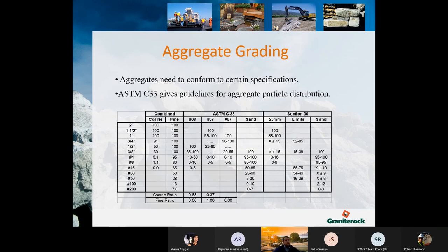There are common gradations for concrete, and ASTM C33 really gives the guidelines for that. A common one is an 08 gradation. So that's going to be a 3/8 pea gravel, essentially. A #57 is a 1-inch gradation. A #67 is a 3/4. And then ASTM also gives guidelines for sand. So for granite rock, if you ever use our mix designs, they'll actually start with the rock size. So our mixes will be either a #8 followed by numbers, a #57 or a #67. This tells you that it's a pea gravel, a 1-inch mix, or a 3/4 mix.